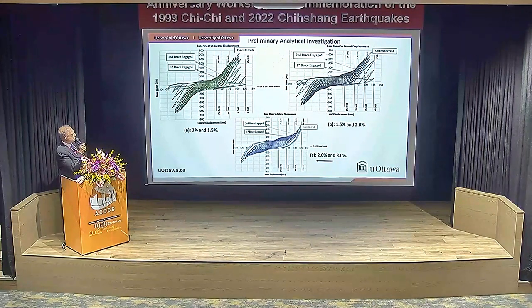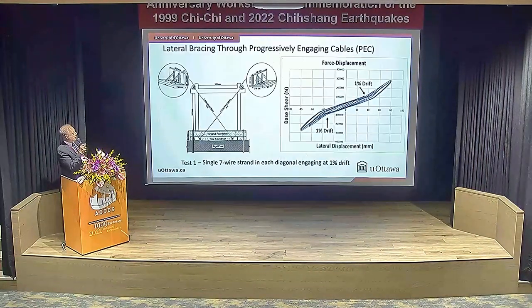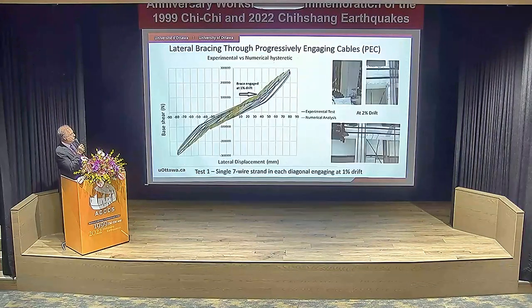Before concrete crushes, that would be our limit. We were able to get 2.5 to 3% drift. And then we tested some frames, and we pre-stressed them. There were a lot of efforts at the ends to be able to pre-stress. And on the right-hand side, you see the results of single brace engaging at 1% drift, and hysteresis curves start showing increased stiffness beyond 1% drift.